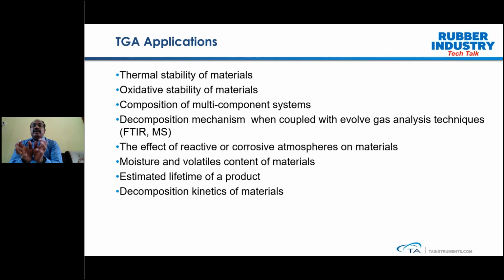In this case, we couple the TGA with either FTIR or mass spec, and that also gives further information on what type of evolved gas is coming out. This will also give a clear understanding about what type of decomposition byproduct is evolving from the sample, and many times it also helps us to identify the polymers. So if you want to have a better understanding about what is coming out of the sample, you can make use of TGA with evolved gas analysis.